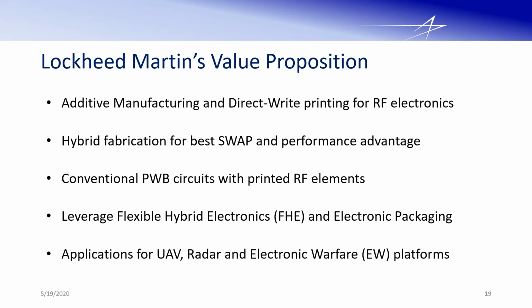And then we go in and we print specific elements where it makes sense to take advantage and get a SWaP reduction. And if you're not familiar with that term, SWaP is size, weight, and power. So in this case, it's specifically size. We can use bare die instead of packaged SMT type devices and print interconnects to the die. We can reduce the footprint versus a wire bond. We can reduce the parasitic losses of a wire bond and eliminate the tuning that's associated with wire bonds.